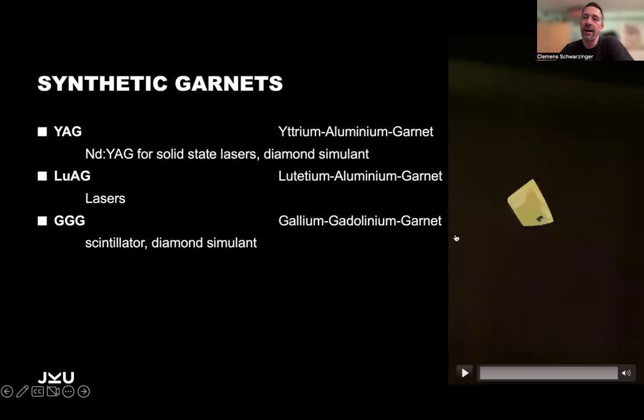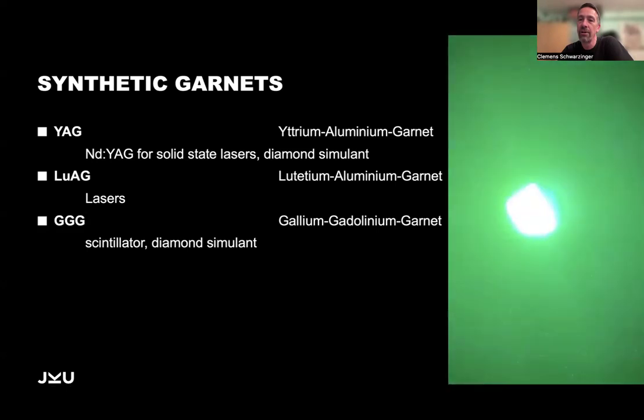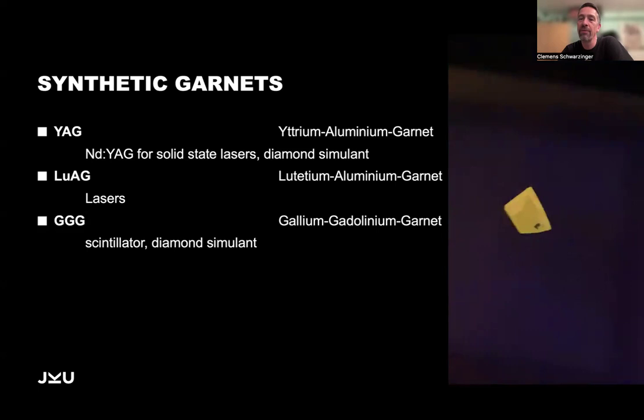So on the right side, I have here a piece of LuAG, unfortunately not yet a gemstone. And this LuAG will now be seen as it is under dark light. So you see it's a nice yellow color. Then I put here aside to the right side a UV source, put it again off, put it again on. And then I use the UV source and directly point at the garnet. And you will just see how it looks. It glows, and now, wow. So this is what happens if you shine a UV laser onto a piece of lutetium aluminum garnet. So this really starts to glow in the dark.